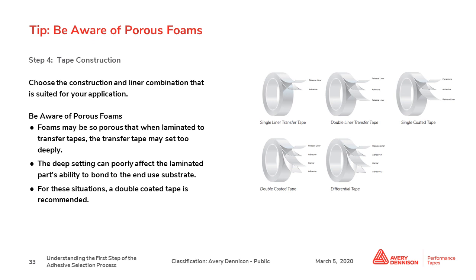So in that situation, if you have a poor coat weight of adhesive where you're needing to bond the substrate, you might not have enough adhesive to really adhere to the substrate. So for that example, we would recommend that you work with a double-coated tape as well. In that situation, the carrier would prevent the tape from overly laminating within the foam, and it creates a barrier so that there's a nice clean coat weight on the substrate side of the tape.